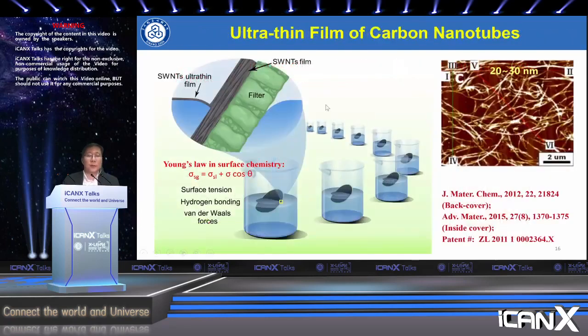For the sensing materials, we usually like carbon nanomaterials, including carbon nanotubes, graphene, and even conducting carbon black. Here we developed a process which works at the liquid-gas surface for layer-by-layer exfoliation of ultrathin carbon nanotubes. It is governed by Young's law in surface chemistry. The surface tension of the solvent plays a very important role. You can see here that we get a very clean network of single carbon nanotubes, with a thickness of about 20 to 30 nanometers.